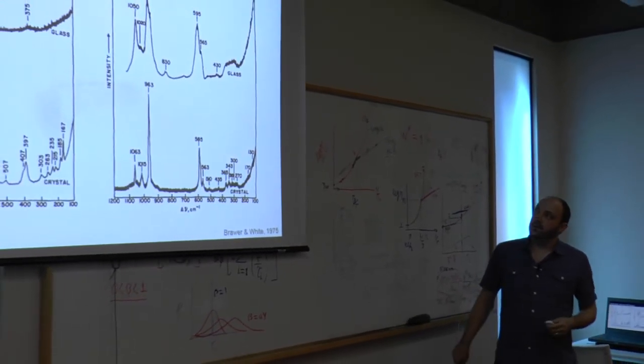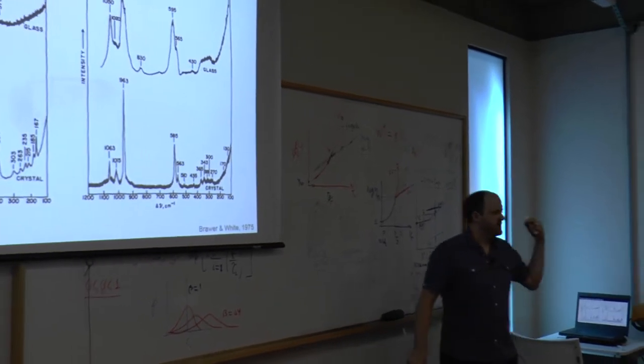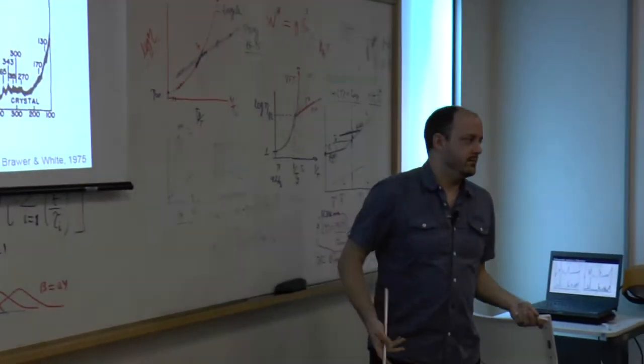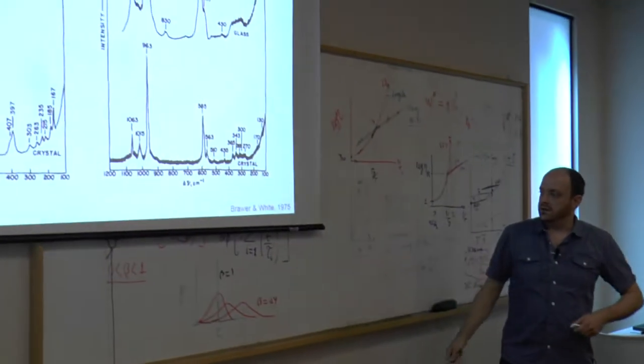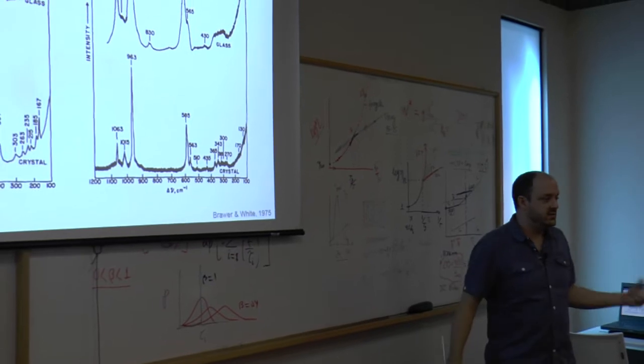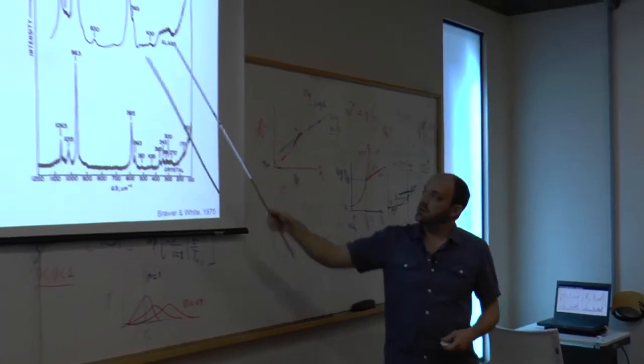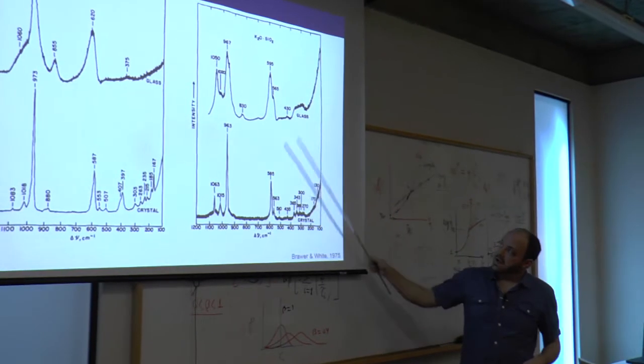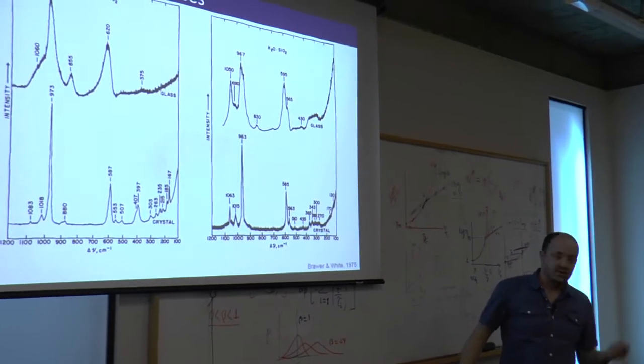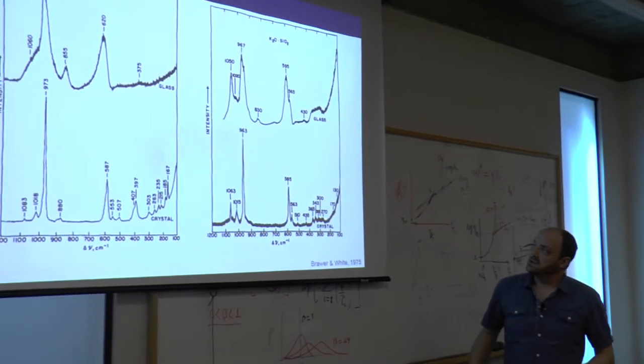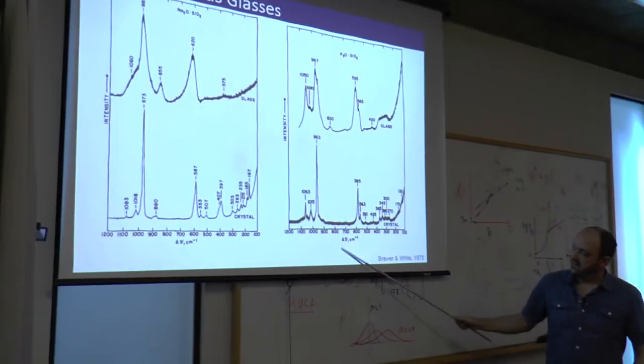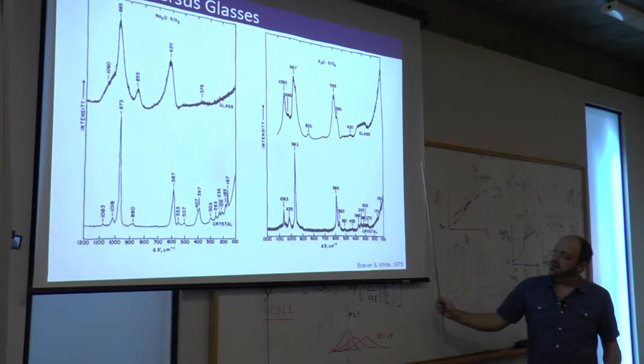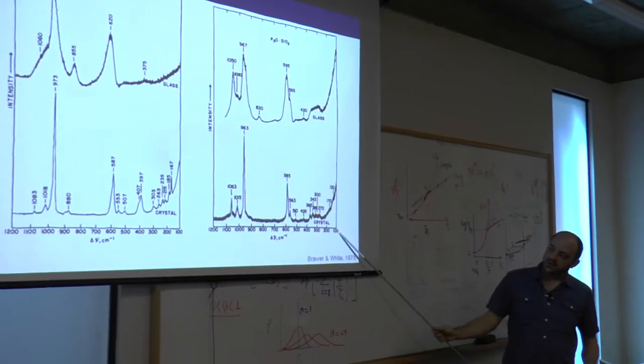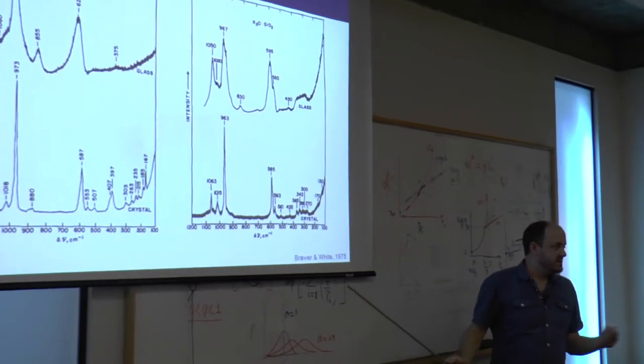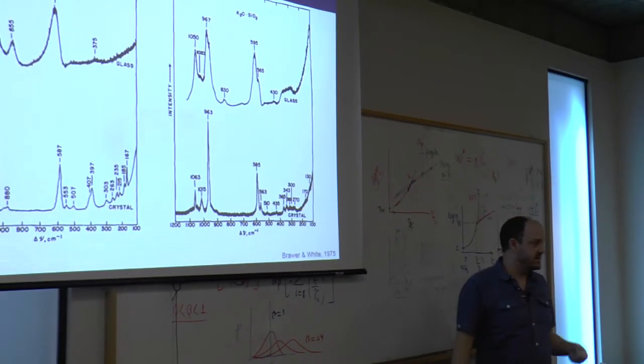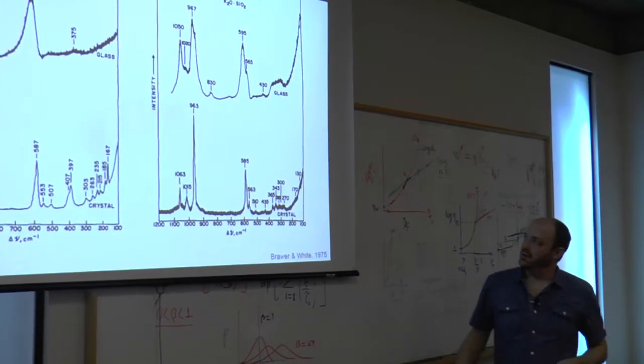The next thing I want to look at is where these ideas about QN species and the structure came from. And this is a classic paper from Brawer and White in 1975, and they took potassium, sodium, and a couple other compositions and made glasses from the mineral and melted them for a while and then quenched it really fast, just in your standard process. And what they observed, here they have the frequency shift, and here the excitation line 0 is over here, and it increases that way. For some reason, people plot it 0 at one side or the other. It doesn't really matter, so long as you can compare in the right way.